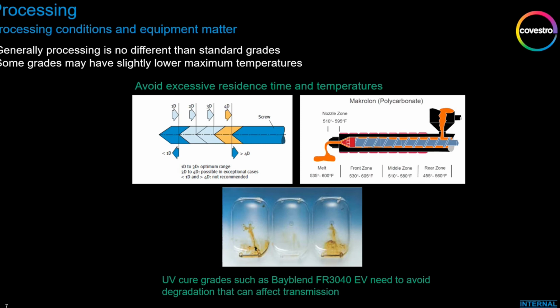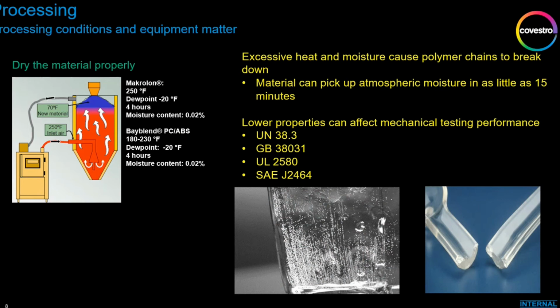For example, if I'm going to try to UV cure a part through that adhesive through that part, then now I have all of that discoloration. I'm blocking my UV transmission. Another thing is I have now potentially degraded the material and lost mechanical properties. So we need to be able to, during the design process, consider the processing and make sure we're sizing everything properly for the molding equipment we're going to use.